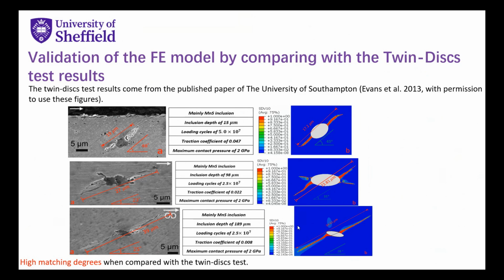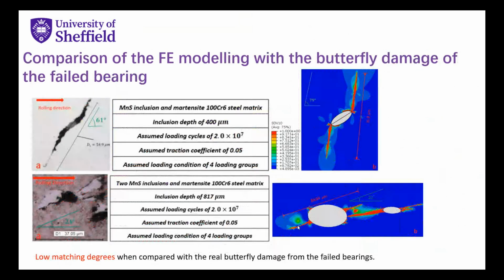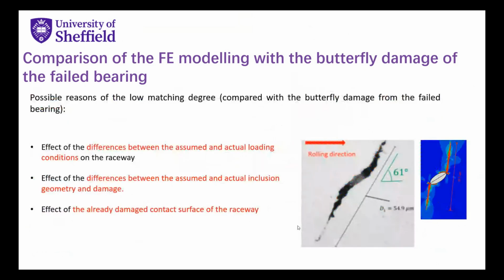I have 3 comparisons here, and I think all the results are very good. But when I use this FE modeling to simulate the real butterfly from the real field bearing, I think the result is not satisfactory, because when I compare the propagation direction and the length of the butterflies here, they have a very large difference from the real butterflies in the field bearing. So I think there may be some problems here.